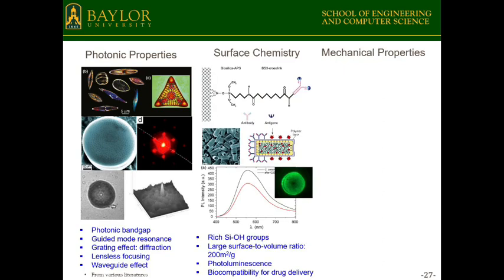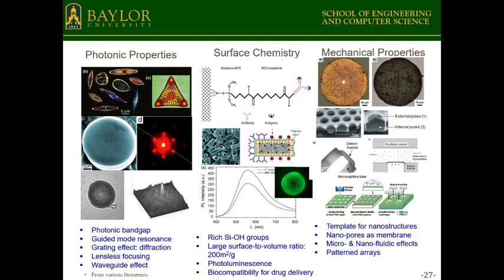In addition to that, this diatom material also offers a very rich surface chemistry, because the surface has a lot of hydroxyl groups. You can easily functionalize the surface, so you can capture the biomolecule you want. It's also a highly porous material with a large surface to volume ratio, more than 200 square meters per gram, and you can easily capture the molecule you want. Also, these nano periodic air holes can be used as microfluidic devices. You force the fluid to flow through the channel, and then you can focus the analyte into the region you want. And last but not least, it's abundant and low cost.